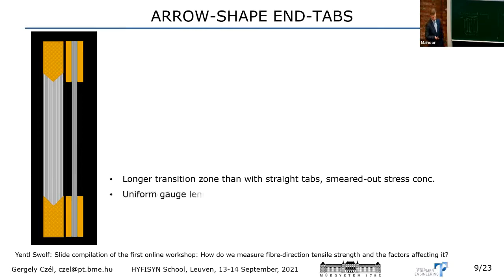And of course, it is designed in a clever way so that the gauge length is uniform, so you can spot a fiber and you can measure if these two angles are the same. All these lengths will be exactly the same, and also it is symmetric also to the mid axis of the specimen and the mid plane of the specimen as well. So there are no unexpected distortions or any naughty effects arising during the test. On the other hand, if we have a fixed depth of the grip, we lose a little bit of the gripping area because of this cutout and this part. So this could be a limiting factor, but I think in most of the cases it is not a big issue.